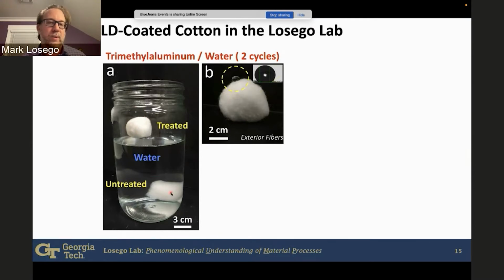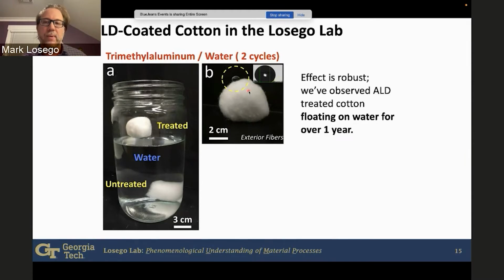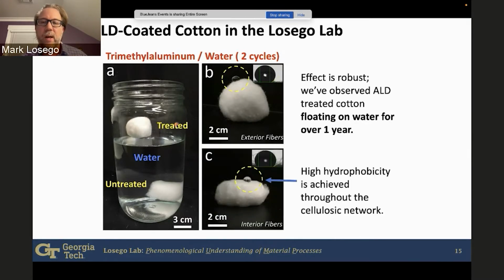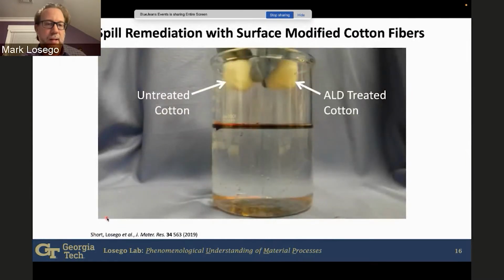The untreated ones soak up water. The treatment is actually fairly stable. It exists for over a year. We've had these floating on water. And if you rip this cotton ball in half, for example, the fibers inside are just as repelling of water as the fibers on the outside. And in addition to that,